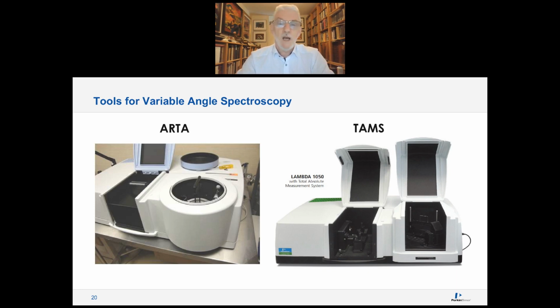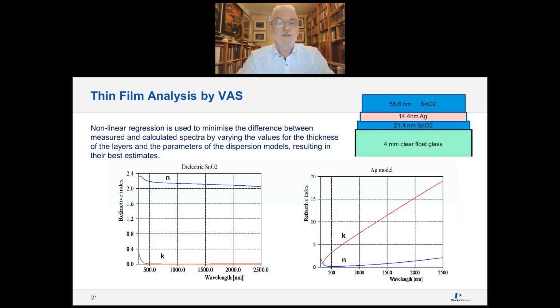I will not discuss them in detail, but I will just show you some of the applications. I discussed in film analysis that one of the applications is to determine the layer thickness and optical constants of the materials in an optical coating stack. And the nonlinear regression is used to minimize differences between measured and calculated angular reflectance and transmittance spectra by varying the values for the thickness of the layers, but also the parameters of the dispersion models. And this example shows you a result of one particular analysis of a 3-layer coating on a float glass sample.